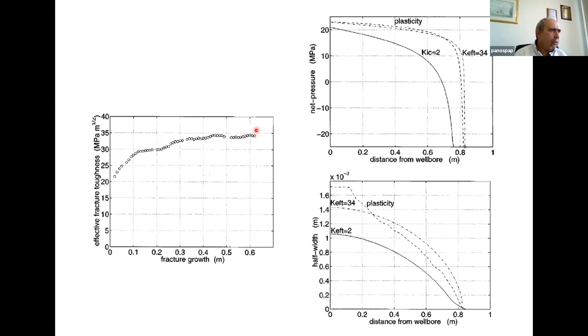It was for a much weaker material. So we got effective fracture toughness 34 megapascal square root meter. And then we use this in the elastic model. I will say now on the top, we have the pressure profiles in the fracture, which is quite close again to plasticity. And in the lower, we have the fracture profiles. In this case here, we don't have a good matching as before. It's narrower, the plasticity near the tip.